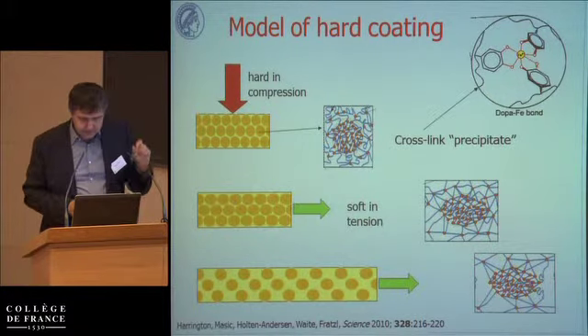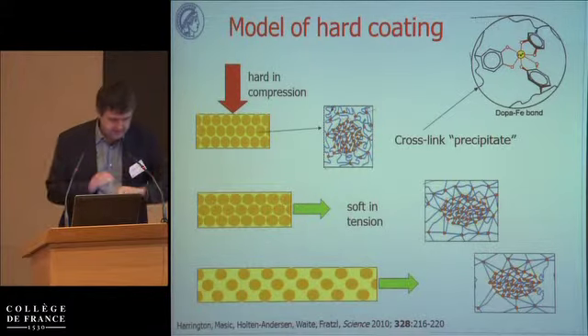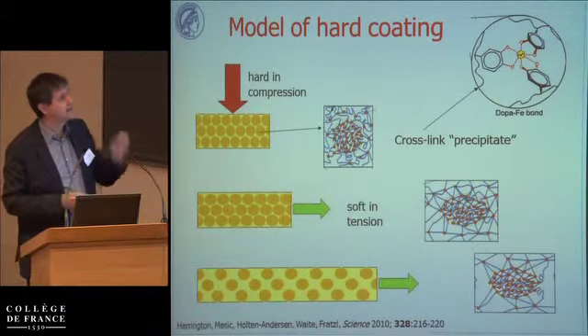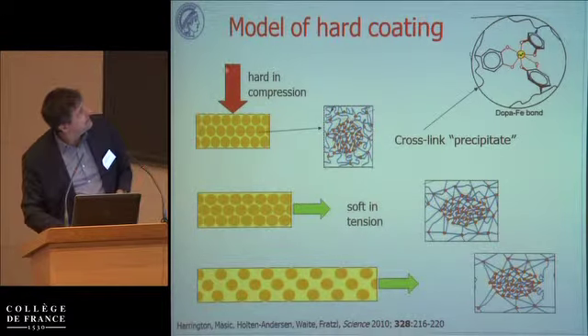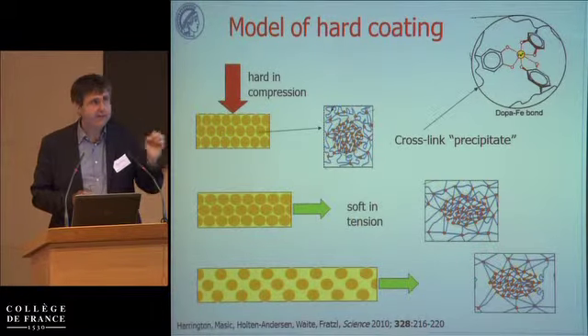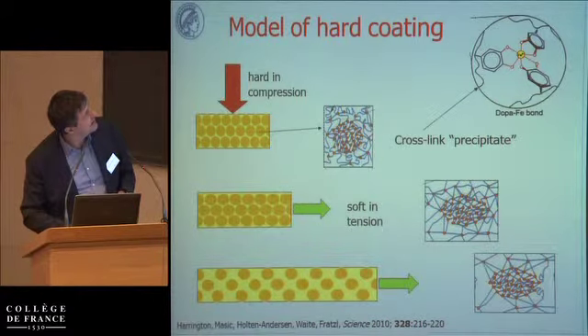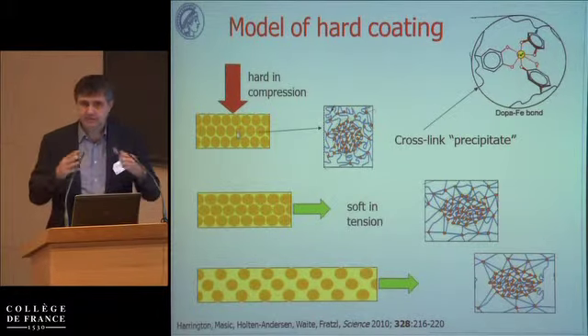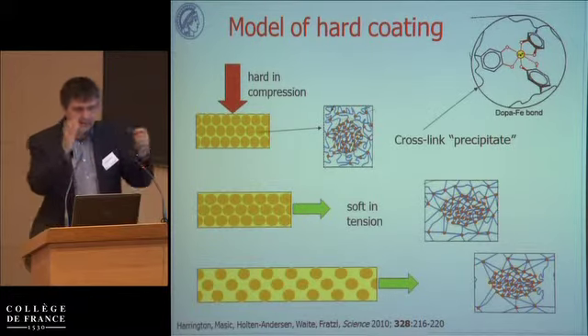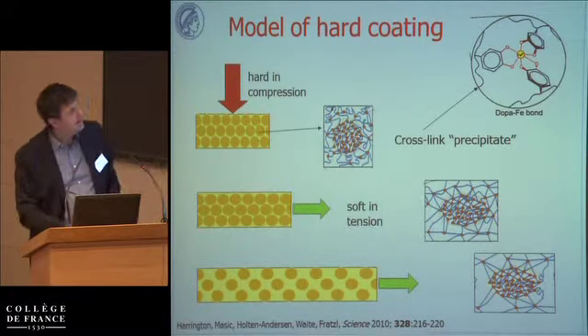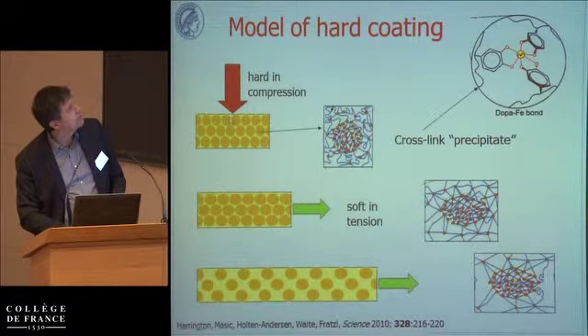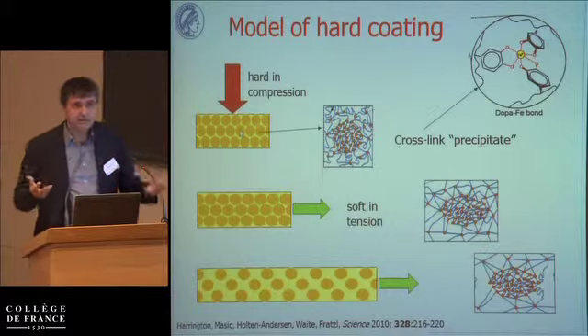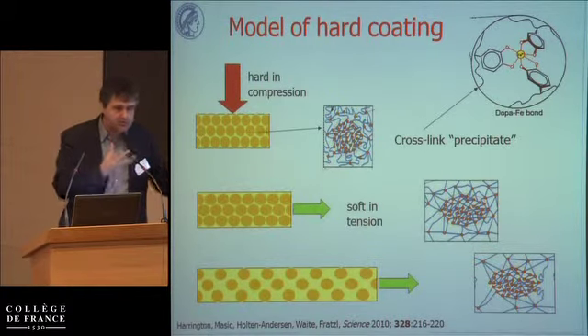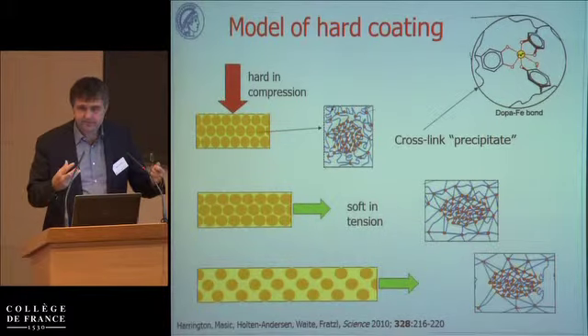So this is now the same picture as before, just to emphasize another very interesting aspect of this material. Namely, here is a hard material, this dark yellow material, but actually the feature that made the trick is that these hard particles are not connected to each other by hard bridges, but by a soft material in between. So the trick here was to take the hard material and separate it into pieces, and even though it's separated in pieces, if you use it in compression, the pieces touch each other and it is almost as hard as a continuous hard phase.